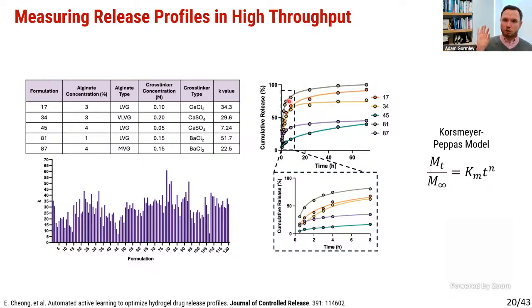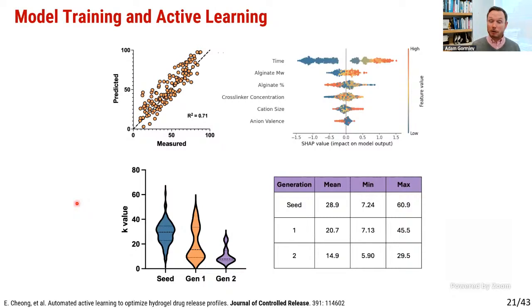So because we're trying to minimize K, that was the value we were trying to optimize within our active learning campaign. Basically, how low can we go in terms of K? How zero order of a release profile can we get with the system? And what you're seeing are lots of different K values that the system was trying to optimize. And the model did a very good job.